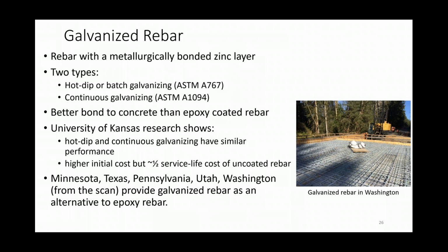And on this topic, we heard from University of Kansas again. So Dr. Darwin came, and their results show that both hot dip and continuous galvanizing essentially had similar performance. They had some lab testing and field observations to show that. And they did run some service life analyses. They reported that the rebar has a slightly higher initial cost, but you can get about half the service life cost as compared to uncoated rebar.